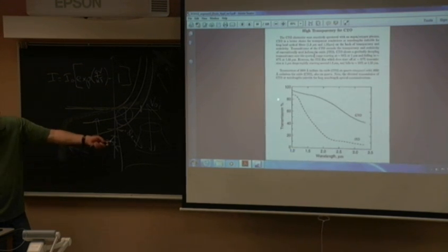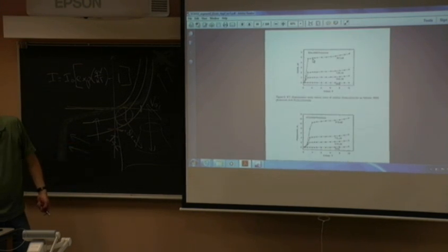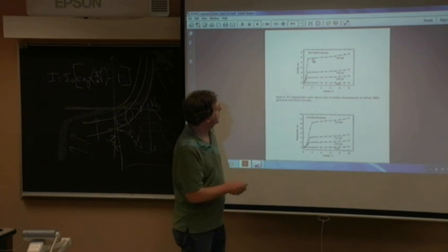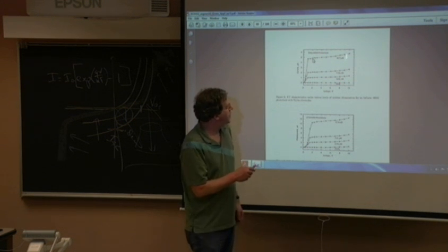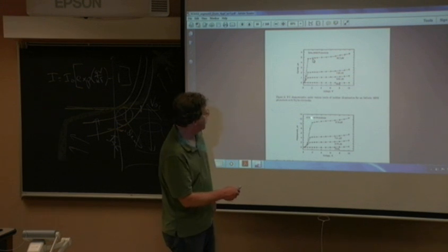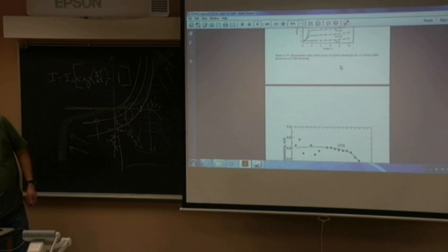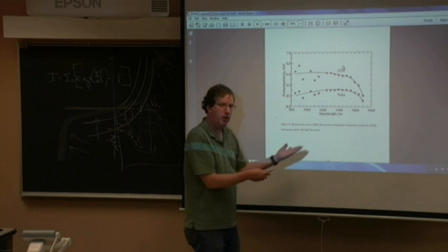This is some work we did and how it looks. We've used some transparent conductors, instead of metal. And here you can see, as we bias it, we can go from an MSM photodiode with metal, and we can get 16.7 microwatts out. But if we use a transparent conductor, we can get more energy out, more current. It was an old piece of research where basically I'm going from a metal that shadows the active region to something that's transparent.